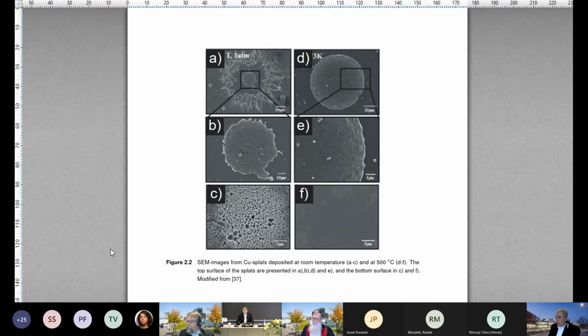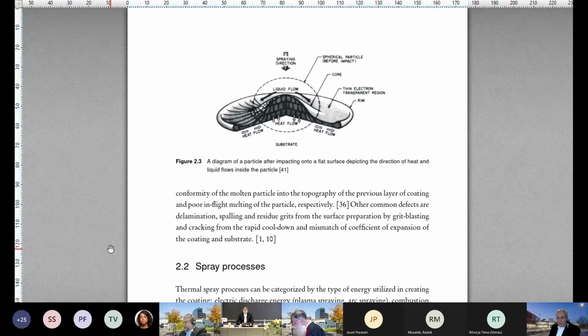If I still go deeper, if it's not ceramic, then in the following picture, 2.3, again, the dynamics of the splat formation. How would you use this type of image and take into account the important ingredient in development of these coatings in this thesis, which is the nanomaterials? How would the nanoparticles show in this type of image? I think it would be the same image, but on a smaller scale. Of course, if they're very molten, they probably wouldn't stay nano. There would be crystal growth in this case. So maybe a splat so flat would need to be very molten and not nano anymore. But that's a tricky one.